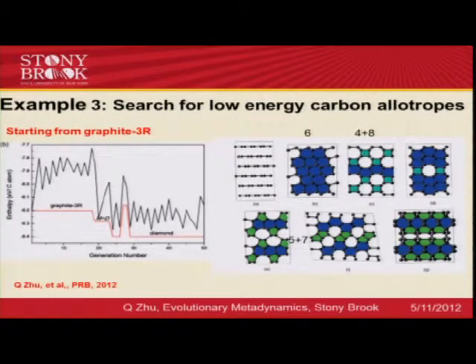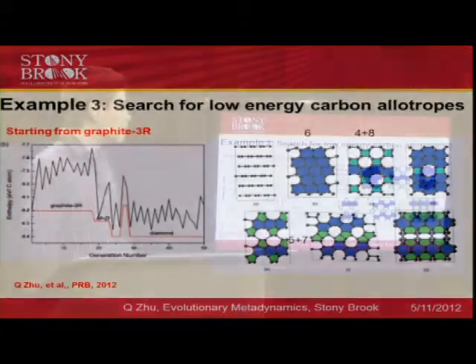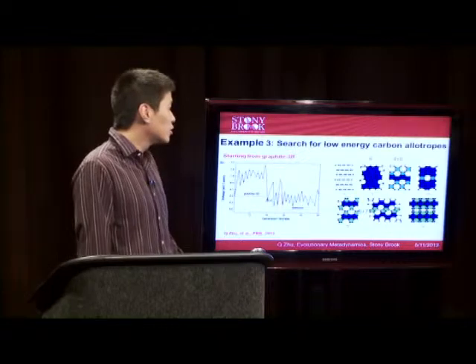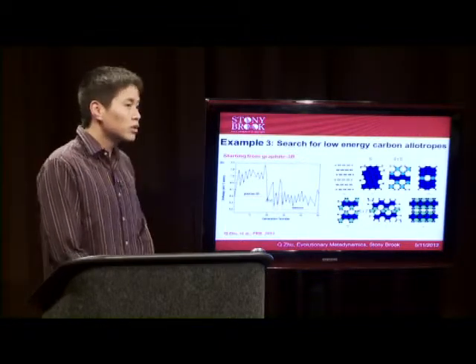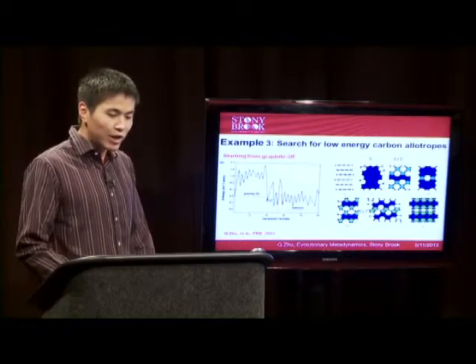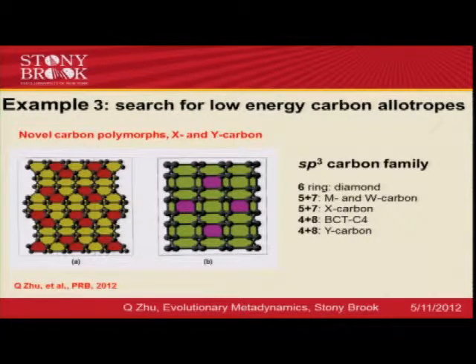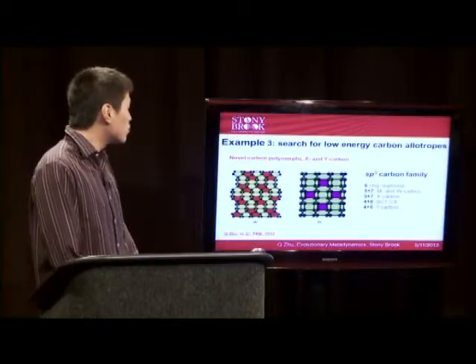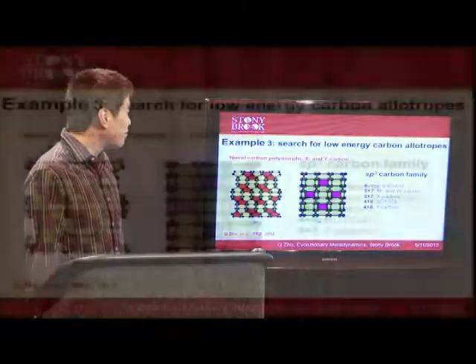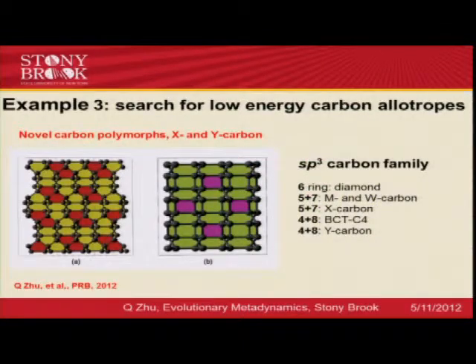In these two single calculations, we actually reproduced all of the previously proposed models from different methods. Most strikingly, we also found some new polymorphs with new topology: X-carbon, with another type of five-plus-seven membered ring topology, and Y-carbon, with another type of four-plus-eight membered ring topology.